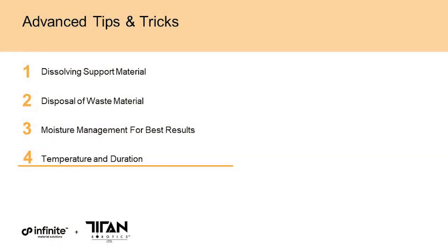The last tip I have for you is the maximum time at temperature for AquaSys 180. After a certain period of time, this material will start to lose its solubility. It'll still print and be rigid, but if you leave it at temperature for too long, it'll be much harder to dissolve. At 160 C, it'll take over 24 hours before you start seeing a solubility loss. At 170 C, it's closer to about 6 hours before you see a drop off in solubility. And at 180 C, you only get about an hour or two at that temperature before your solubility is going to be affected.